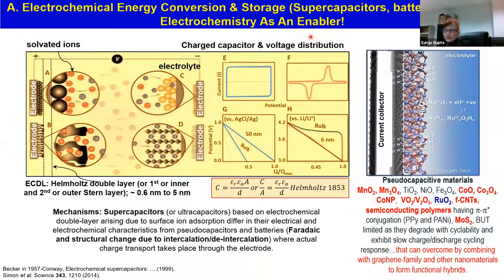So where did it all begin? Back in 1957 was the first realization. What happens when you have a metallic electrode submerged in an electrolyte, an aqueous electrolyte for instance, is that at the surface when you apply a potential, there is a positive charge on the electrode, and in order to balance that positive charge, the corresponding negative ions start to accumulate right next to it. As a result, it forms what we call the double layer, which is similar to a parallel plate metal capacitor.